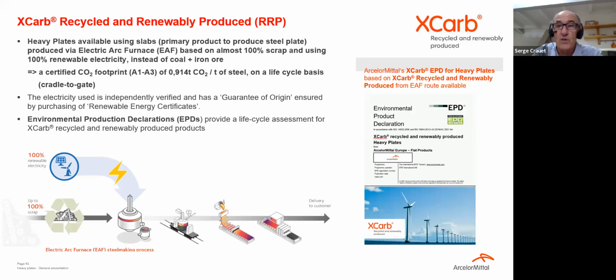With almost 100% scrap. So we say almost because you can have some cases where you have to use something else, but very close to 100%. And why? Because you have a better performance in the A1, A3 section, so a lower value for CO2. So that's why we decided. And using, of course, that's the definition of the RRP, 100% renewable electricity.